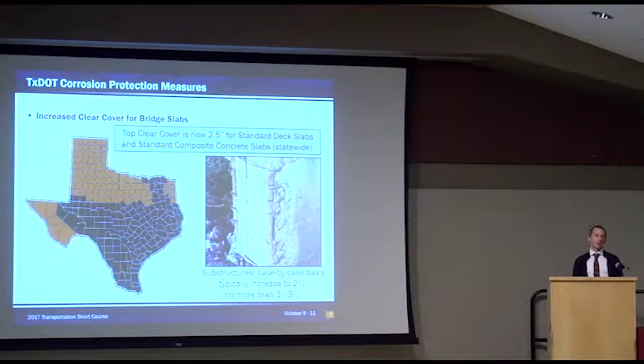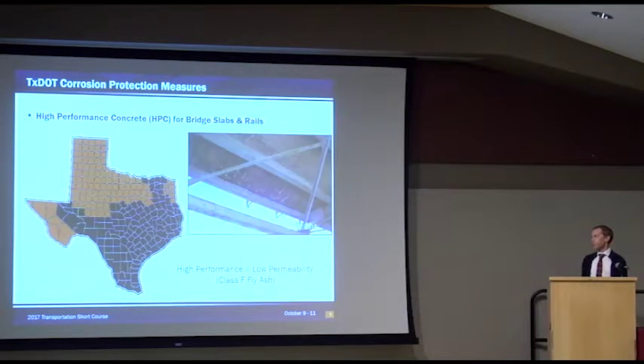So what you'll see, at TxDOT we do a really good job with our concrete, and that's our first line of defense against corrosion. First thing we do is bump up the clear cover. Now, these recommendations were issued in 2013. Since that time, we've decided to go with 2.5-inch clear cover over the top mat of reinforcing in all of our bridge decks. But the substructure also needs attention a lot of the time, and in a highly corrosive environment, we say go ahead, case-by-case basis, if you need to, bump that clear cover up to 2.5 inches, maybe 3 or 3.5, but too much more than that, we're talking about unreinforced concrete, and that's a whole other problem.